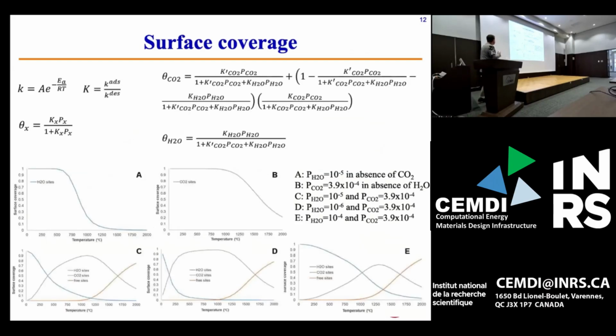We developed a mathematical model based on Langmuir adsorption theory, which takes into account competitive co-adsorption between CO2 and water, and also competitive evaporation between CO2 and water. I won't pass you through those equations, but we can discuss later if you're interested.